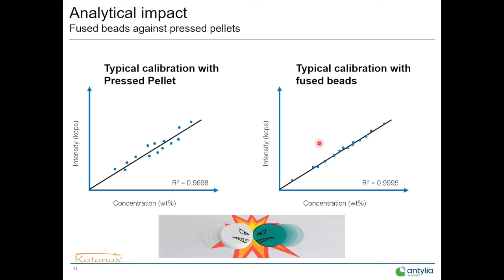During the time the fusion is going on, we will look at different analytical impacts and advantages of fuse bead compared to other techniques. In this case, we will compare two solid preparations: press pellet, which consists of pressing a powder sample and presenting it directly to the XRF, compared to the fuse bead. You can see here a typical calibration curve you can obtain with press pellet and fuse bead. You can see quickly that you have more precision and more accuracy with fuse bead.